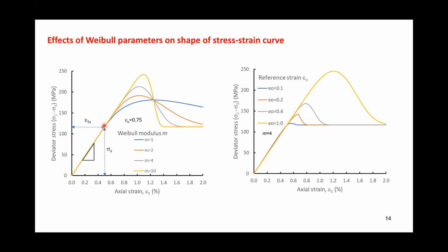Again, the material starts to yield here, epsilon_y and sigma_y. This slope is equal to Young's modulus. This illustrates the effect of the Weibull modulus. As I said, it's a measure of the brittleness of the material. For this case, we use a reference strain epsilon_0 of 0.75.